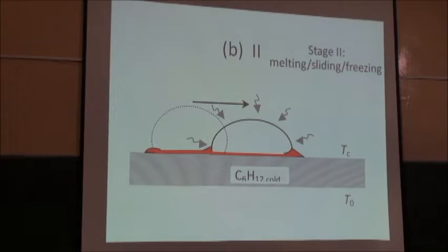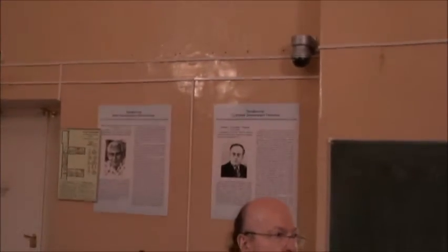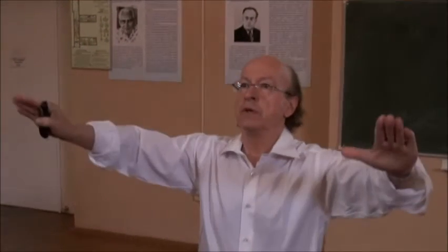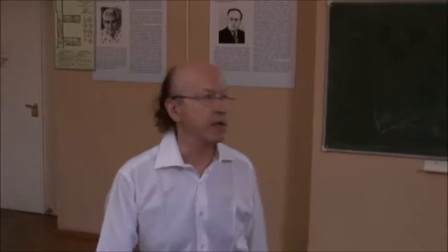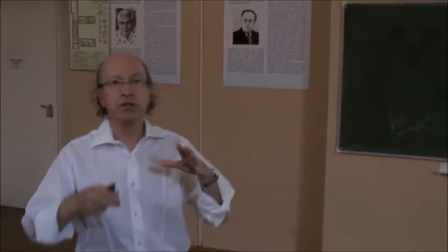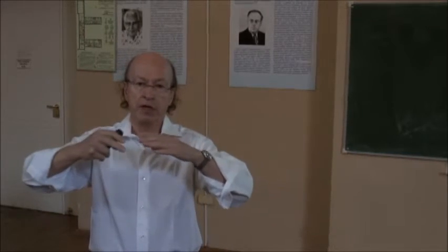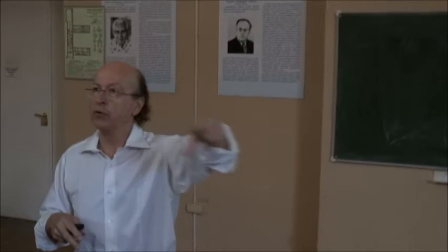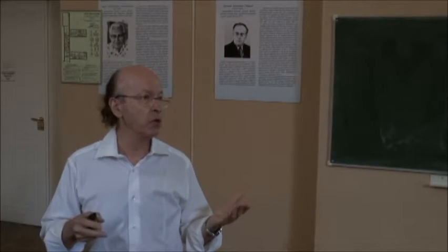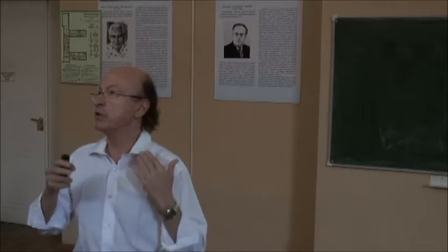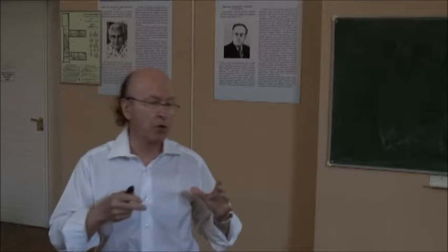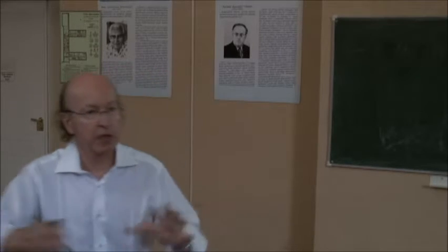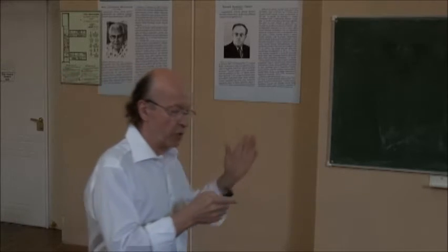When the drop grows, it is pinned, so the contact angle goes to the advancing contact angle. When it is not pinned, it spreads, and there is always a capillary force, and the balance of the capillary force around the perimeter is not zero because the perimeter is not strictly circular. So there is always a force that will move the drops in some random direction.